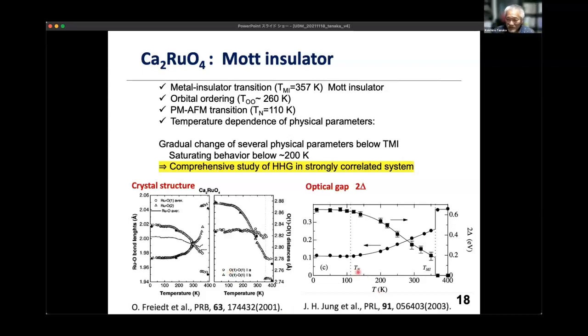Yes. As you mentioned, around the antiferromagnetic phase transition, some change occurs or not, and we cannot see any change around the magnetic transition point. Also, we checked the mixed crystal. By adding strontium, we can modify the magnetic phase transition temperature, and also control the band gap energy, but we obtained no significant change around the magnetic phase transition. Okay, thank you. Vishal, please.